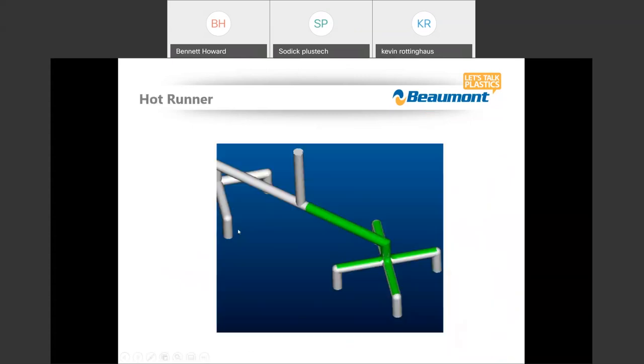So in a hot runner system, the longer this sprue or your nozzle, right? So sometimes with really big molds that have 6, 7, 8, 9, 10-inch long, 12-inch long nozzles, that shear profile is developing there. Our shear profile is developing the moment we start pushing on plastics in the injection molding machine. The minute those laminates start moving forward and progressing towards that nozzle and into the nozzle, that shear profile is forming. And so with hot runner molds, if we have sometimes shorter ones here, we maybe see less of an impact into the multi-cavity tool.